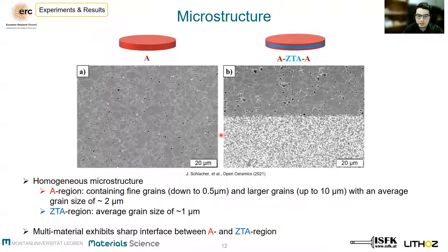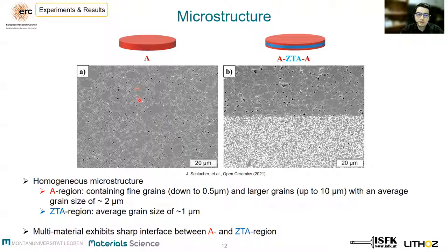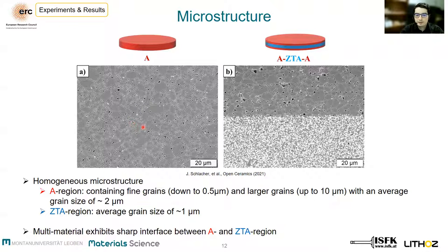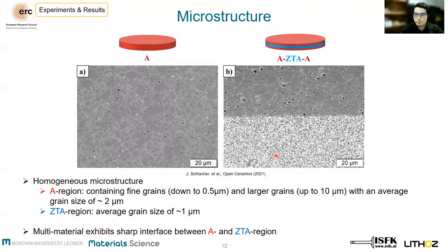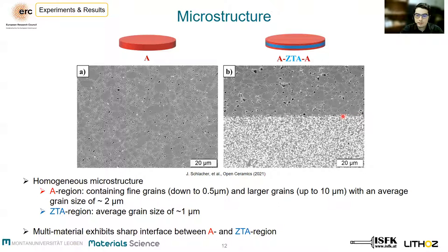Looking at the microstructure, we see that in the alumina part the microstructure is homogeneous with a rather fine-grained structure, a mean grain size of approximately two microns and low porosity content. This is very similar to the alumina region in our multi-material system. In the zirconia-toughened alumina region of our laminate, the average grain size is much smaller than one micron. Furthermore, it is worth highlighting that we have a very sharp interface, which can be traced back to the appropriate sintering conditions and a clean multi-material printing process.